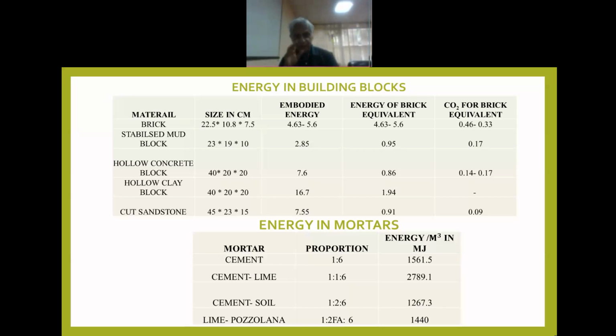If you add lime, the setting time is increased. But unfortunately, 1:1:6 cement lime mortar also consumes even more energy than cement. So this is not a good alternative if you want to reduce energy. But if you add soil to cement mortar, this is not accepted by our National Building Code. But we have found by our experiments over the past 40 years, to add a little bit of soil, 1:2:6, where it is a cement mortar, but along with sand, you have 1/3 of the sand provided in the form of soil. You find that the energy comes down to 1267 megajoules per meter cube, and the setting time is increased to 2 hours or so. So this cement soil mortar you can mix once and use in the next 2 to 3 hours.